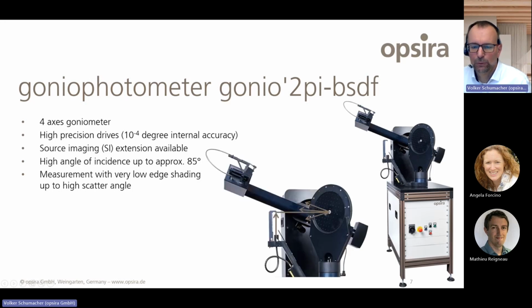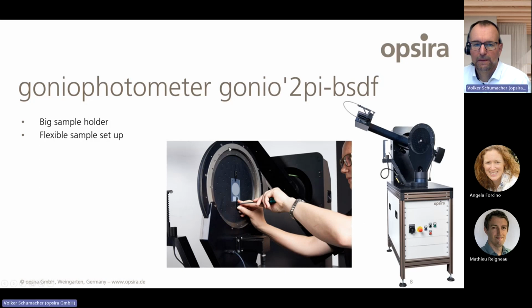The principle is like we can see it here. The light will come from the below side. It goes up, it's a collimated light. It goes up to that redirection mirror. This redirection mirror brings the light to the sample. The sample is mounted here. The sample itself can be rotated about on its own axis. And here is the detector, and the detector can surround the sample and measure the scatter characteristic.